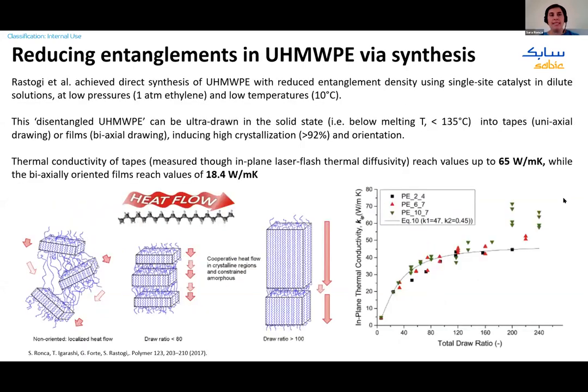And during my time at Loughborough University, I worked together with Professor Rastogi on a synthetic pathway that allowed us to synthesize ultra-high molecular weight polyethylene directly with a reduced number of entanglements. So if you synthesize it using single-site catalyst in dilute solution, at low pressure and low temperatures, what you get is a disentangled ultra-high molecular weight polyethylene that can actually be ultra-drawn in the solid state. So you don't need to go into the melt.